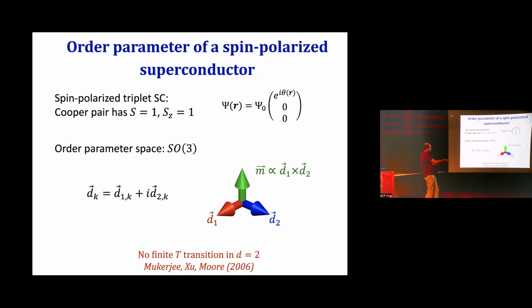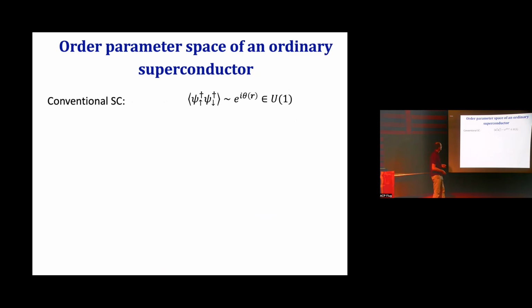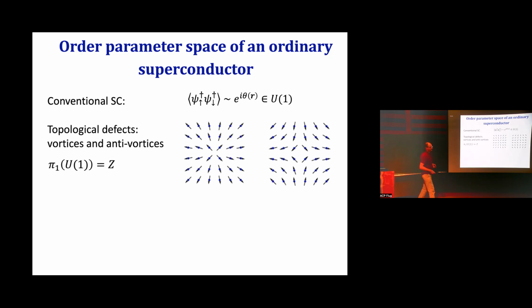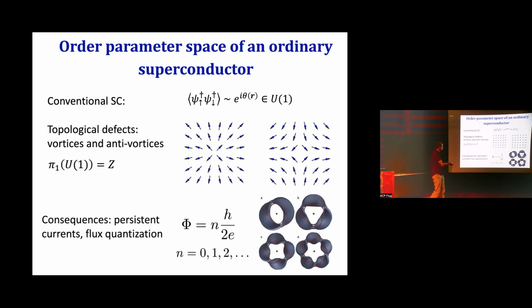It turns out that there's still something special about this type of order parameter that I'd like to point out. In a conventional superconductor, the order parameter space is the phase. Order parameter is a complex number, and that means that the order parameter space is U(1). That has interesting consequences. The topological defects of such a superconductor are so-called vortices and anti-vortices, and that has some dramatic consequences. We know that leads to flux quantization, the existence of persistent currents, and so on. That's all related to the fact that these defects are characterized by an integer number. A complex phase going along a closed path in real space can wind any integer number of times.